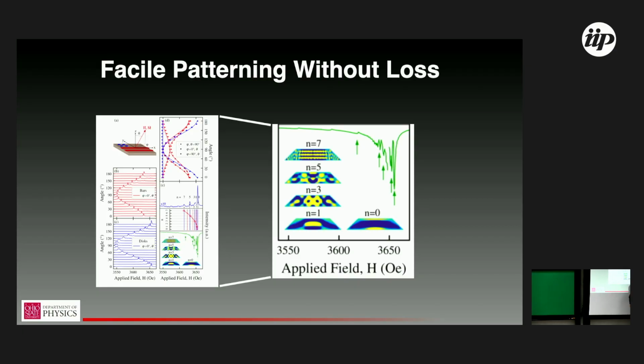That's maybe easiest to see in the n equals 0 and the n equals 7 state, where you have boundary conditions for the n equals 0 state, but basically you see the magnetization rotate once as we go vertically through the structure, rotate many times for the n equals 7 magnon mode, and we have effectively thickness quantization with slight modification from the radial direction, because these are still relatively large structures. That's what gives the n equals 3, n equals 5, this more complicated behavior, because we're having some interaction between those things. The bottom line being here, we can make tailor-ordered magnon resonators. I think that's really what we were excited about with this demonstration. So for quantum magnonics, you can imagine that's exciting.